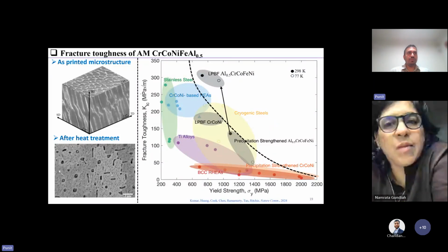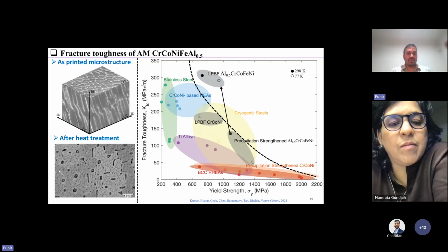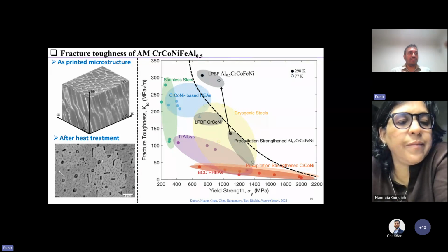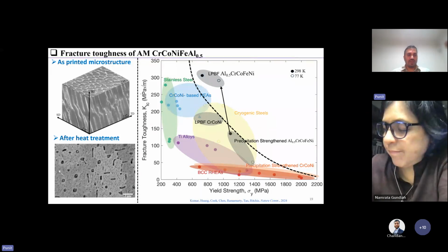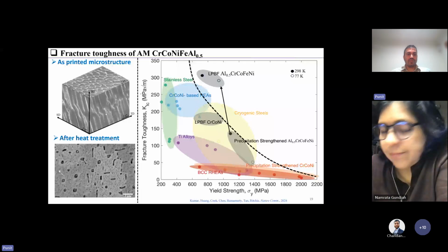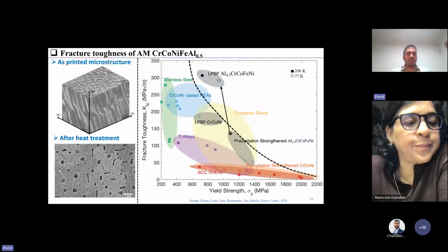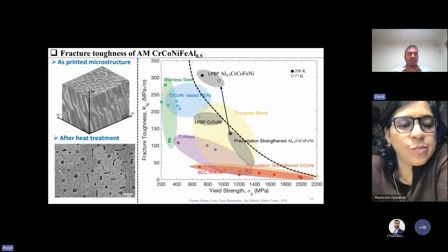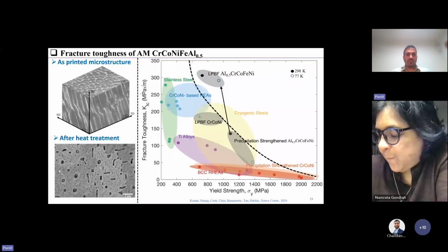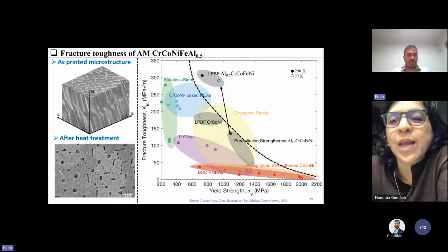So this microstructure is an FCC material. It is not really a stable microstructure, because we are doing fast cooling during the laser powder bed fusion process. So if we do an annealing treatment at about 700 degrees C for 1 hour, we can essentially dissolve this B2 phase inside the matrix, and we can form these precipitates by doing fast cooling.